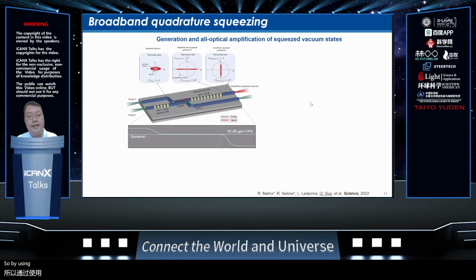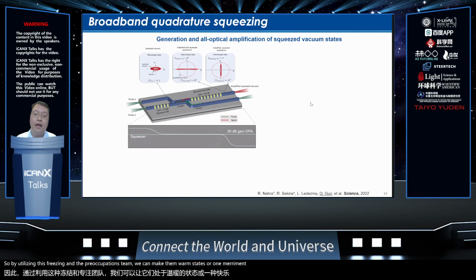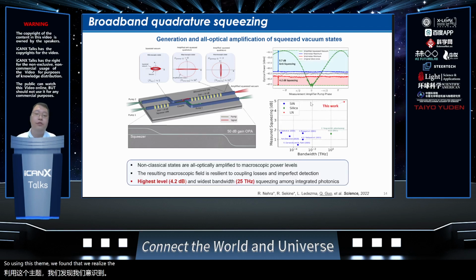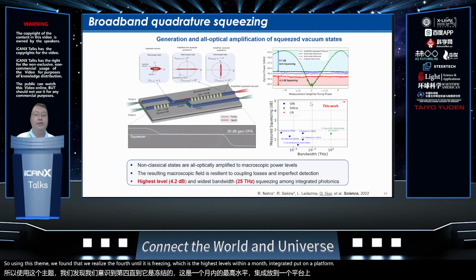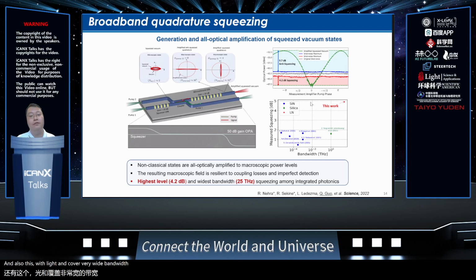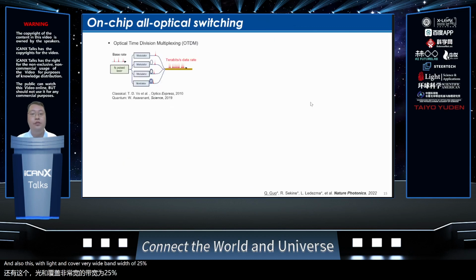By utilizing this squeezing and pre-amplification scheme, we can make quantum measurements much more resilient to optical losses. Using this scheme, we realized 4.2 dB squeezing, which is the highest level of squeezing among integrated photonic platforms. And the squeezed light can also cover a very wide bandwidth of 25 terahertz. In addition to signal amplification, we also want to use the strong nonlinearity of lithium niobate to tackle the grand challenges in ultrafast information processing. By using ultrashort pulses, we can even have a terabit per second data rate for communication or computing.